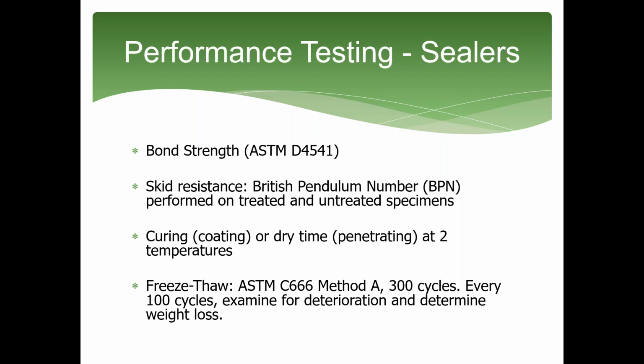Freeze-thaw resistance is performed according to ASTM C666 method A. Every 100 cycles, the sealed samples are weighed and visually examined. Samples are tested for a total of 300 cycles. The samples are evaluated on the concrete deterioration rating scale, and the freeze-thaw weight loss ratio is calculated.